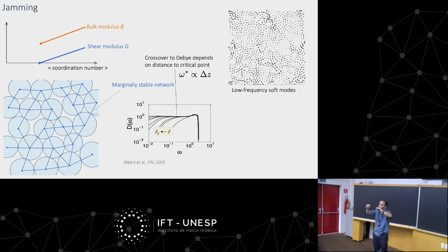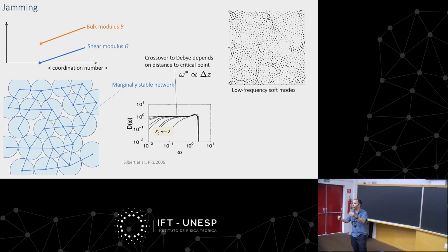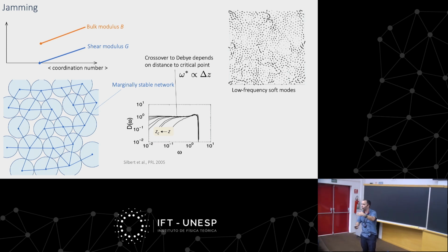There is a gradient term. You can go from this microscopic model into an elastic continuous model. In the elastic continuous model, you have some free energy cost to compress it as you keep compressing it. Even though you start with a model that's microscopic, that only has excluded volume interactions, you can derive some elastic free energy for it. And the elastic free energy will penalize it if you try to do some kind of bulk compression. If you try to compress it, you have to pay some energy.